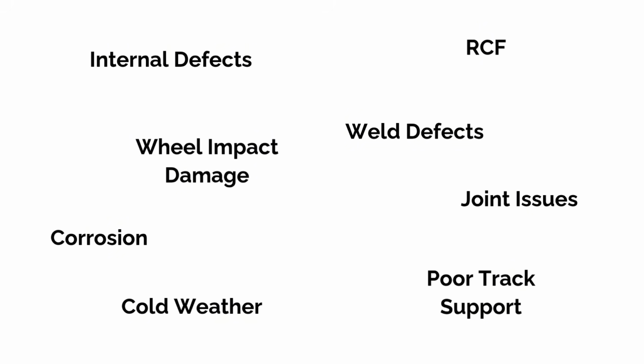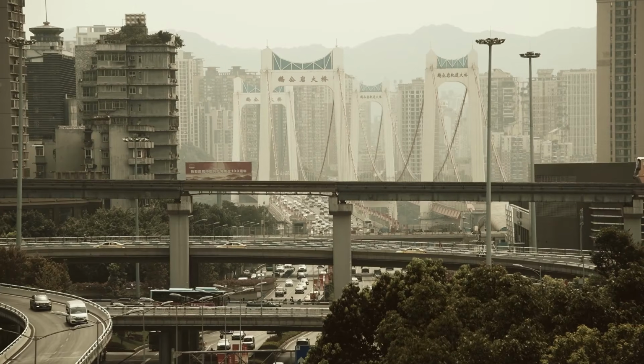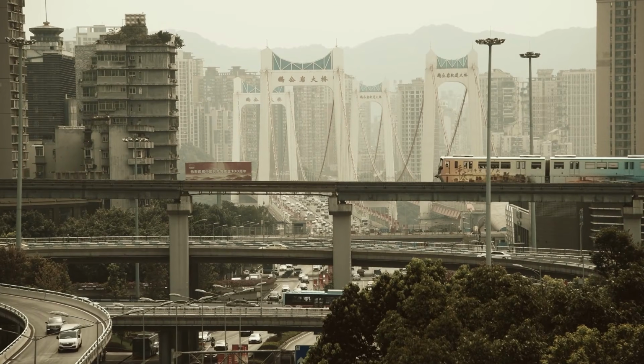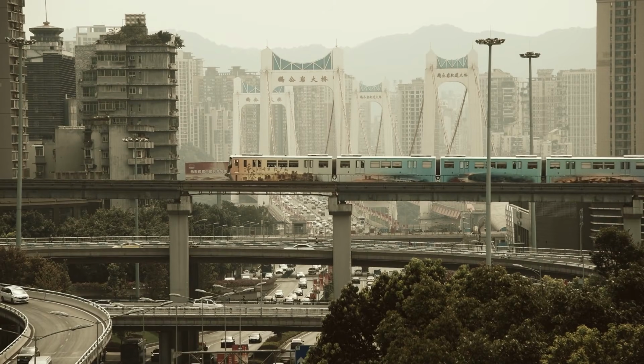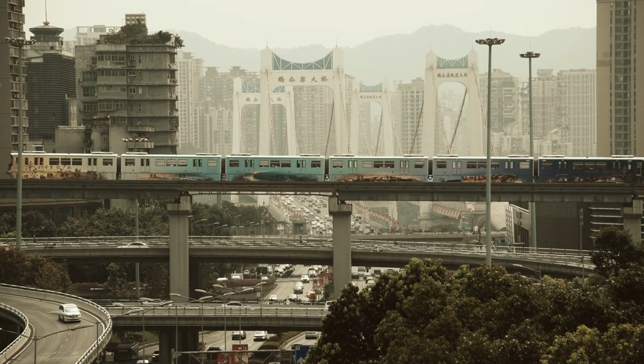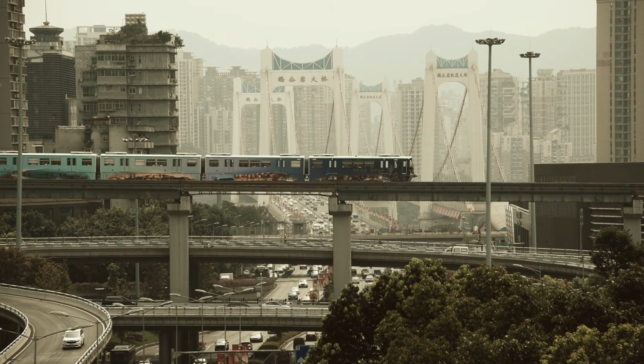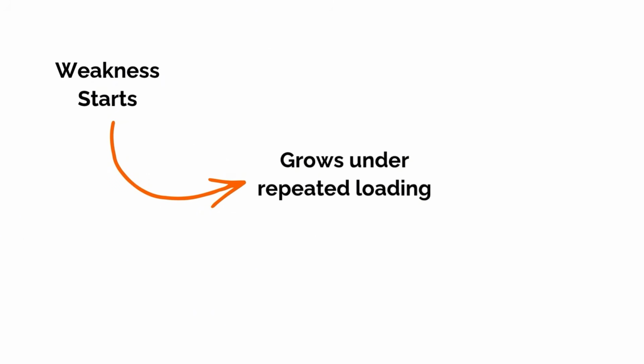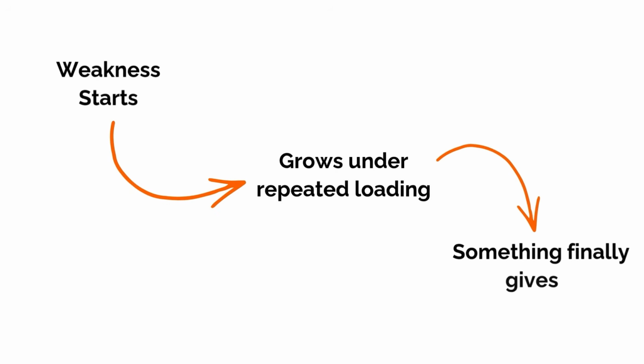So we've covered 8 different reasons for rail breaks: internal defects, RCF, wheel impact damage, weld defects, joint issues, corrosion, poor track support, and cold weather. The most important point, and the real lesson here, is that it's very rarely just one of these issues on its own that causes a rail to break. The process usually follows the same pattern. A weakness starts, it grows under the repeated loading of passing trains, and then something finally gives.